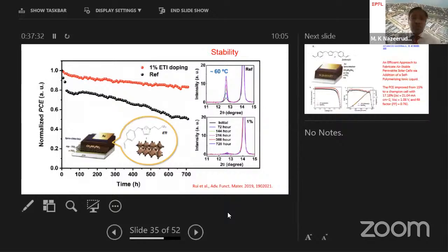Here, just focus on the insert, the reference sample versus with 1% ionic liquid. The XRD data clearly shows the formation of lead iodide at 60 degrees temperature. As time goes on, this formation of lead iodide increases. That's a manifestation of decomposition of the perovskite. And this is not happening when we have 1% of ionic liquid in the perovskite composition.